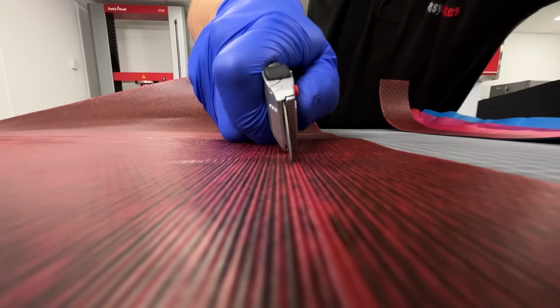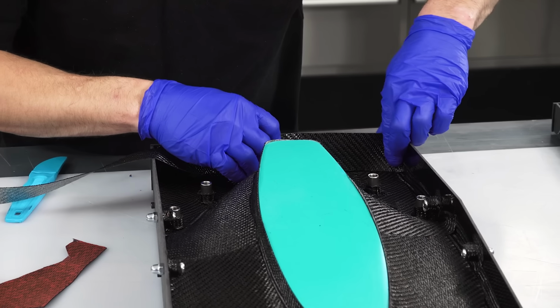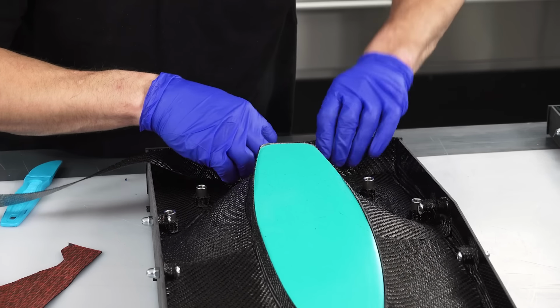The backing plies are now laminated in much the same way as the surface ply, but being heavier, they do take a little more work. For this small mould, I'm going to be doing a 1-2-1 layup, meaning one surface ply backed by two backing plies and then another surface ply to balance. On larger moulds, a 1-4-1 layup would be more typical.